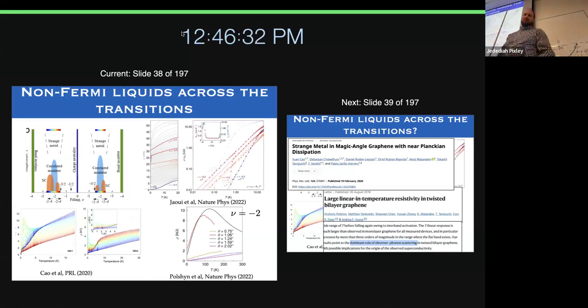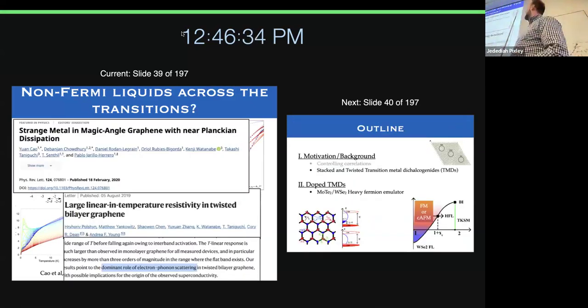So there's really no way right now to ascertain if this is a strongly correlated effect or if this has a phonon-driven mechanism in that regime of temperature that seems to be linear. And so, from my perspective, I think the system is incredibly interesting, but it's still not sufficiently strongly correlated. Yeah, but you have a very, very small Fermi surface.